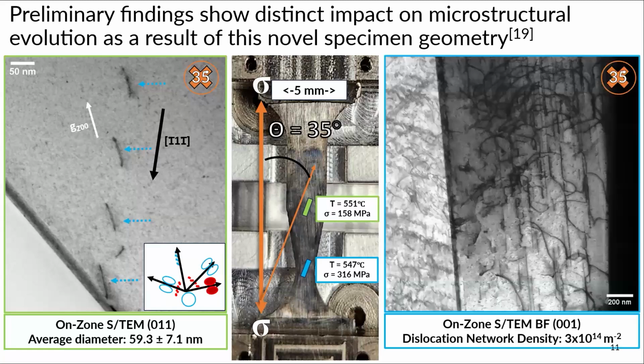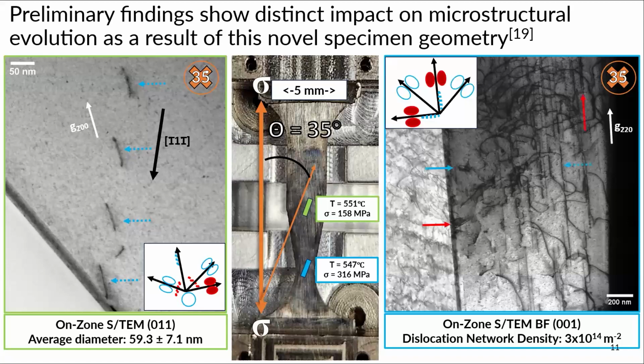And then on the same sample, in a totally different area, in the higher stress area, you have a significantly increased dislocation network. You have a bunch of various different types of loops that are showing up. And there are different orientations for all of these, and I won't go into it because we're short on time. But basically, this proves that our sample can generate multiple data sets. Whether that is inherent to the specimen geometry, we'll figure out.